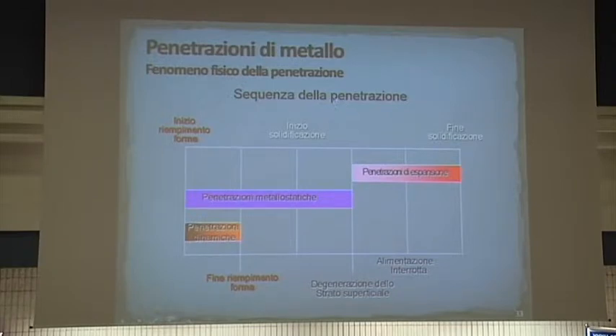So here is a sequence of penetration. As you start with some liquid metal, you have metallostatic pressure that is affecting all the way until during solidification and results in degeneration of the superficial layer. You have dynamic penetration that occurs only as you fill the mold. After that, the metal gets quiet and dynamic penetration doesn't occur. And then you have expansion penetration that occurs during eutectic solidification only for cast iron. And that goes all the way to the end of solidification.